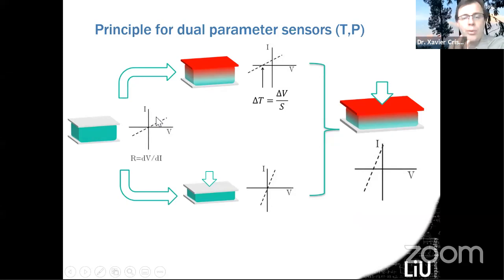Now, if you press on the material, then you change the resistance of the material, you decrease the resistance of the material, and the slope of the IV curve changes. So the slope of the IV curve here is connected to the pressure you apply.